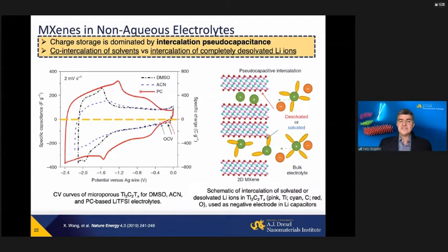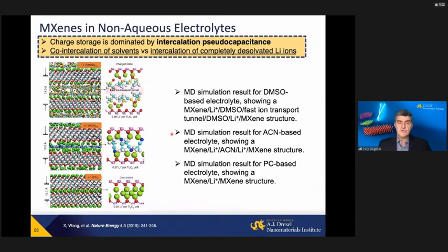Highly conducting acetonitrile solutions, which in a conventional carbon supercapacitor should give the highest performance, actually gave the lowest capacitance, the area under the cyclic voltammogram. And propylene carbonate, with an order of magnitude lower conductivity, gave us a much larger cyclic voltammogram. So what is going on?